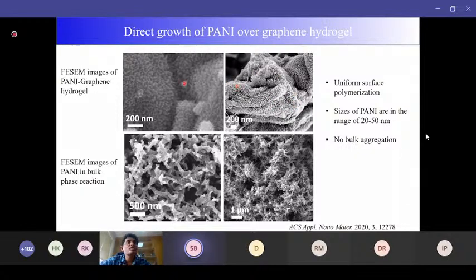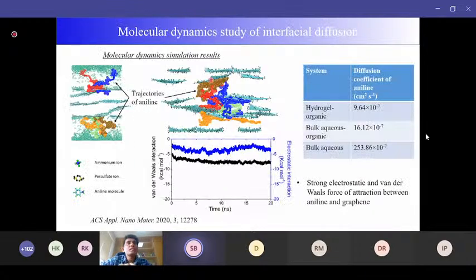If, instead of this particular arrangement, which we named the hydrogel organic interfacial reaction instead of the aqueous organic interfacial reaction, we use it the other way around, instead of graphene hydrogel, then it will give rise to this kind of bulky phase. With this, we have also done molecular dynamics simulation to check whether our expectation is right, that during the passage of the reactants through this hydrogel, there is some interaction of these molecules with the graphene sheets or not.